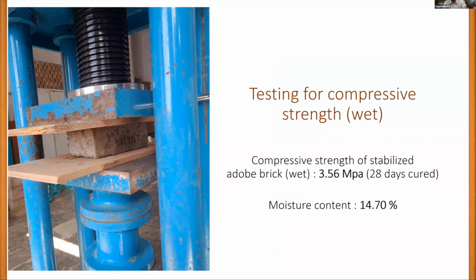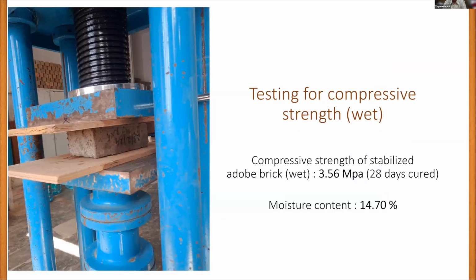The wet compressive strength, what we got with this mixed proportion, was 3.56 MPa for 28 days cured specimen, which satisfies the Bureau of Indian Standards Code requirement to be used as a construction element in the activity. The moisture content is around 14.7%, which is very well within the durability characteristics.